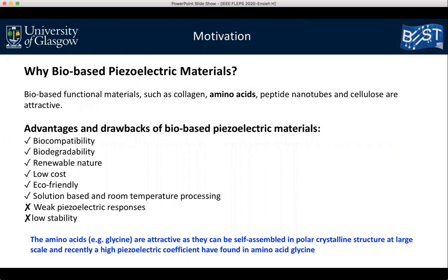Bio-based functional materials such as collagen, amino acids, peptide nanotubes, and cellulose are attractive because they have some advantages such as biocompatibility, biodegradability, renewable nature, low cost, eco-friendly, and solution-based and room temperature processing. However, they also have some main drawbacks, such as weak piezoelectric response, and it's usually difficult to obtain uniform and scalable polarized structure of them, and most of them have low stability in the room environment.